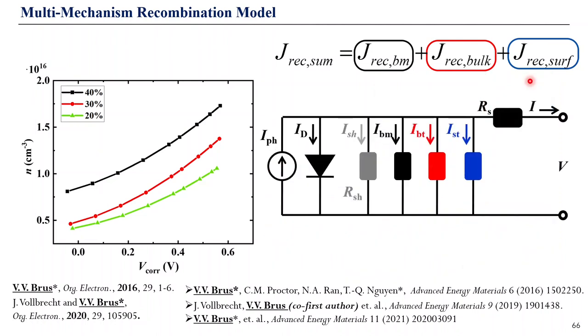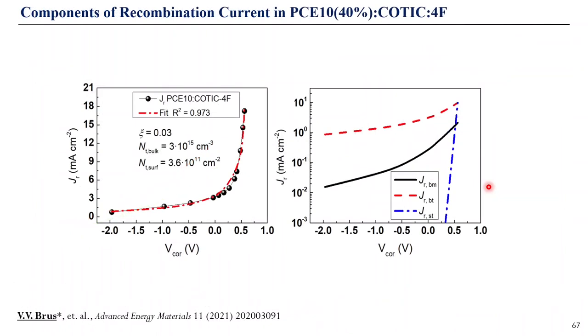So this is quite a nice tool because it allows us to individually quantify each contribution of recombination mechanism and see what is dominating and what's not. So for example, we consider here this optimized PCE10(40%):COTIC:4F system. We feed the experimentally measured recombination current within the scope of this multi-mechanism recombination model, determine unknown recombination parameters,